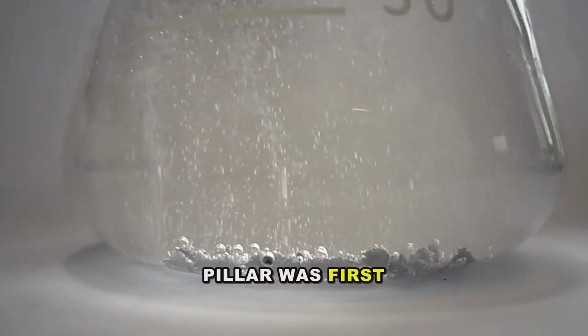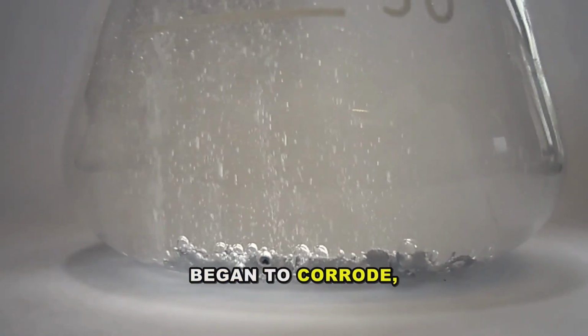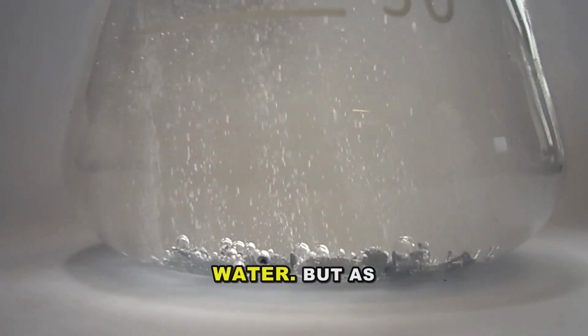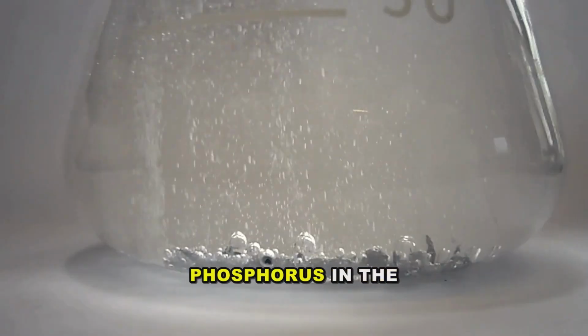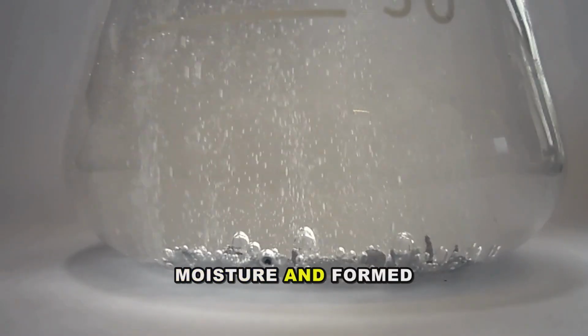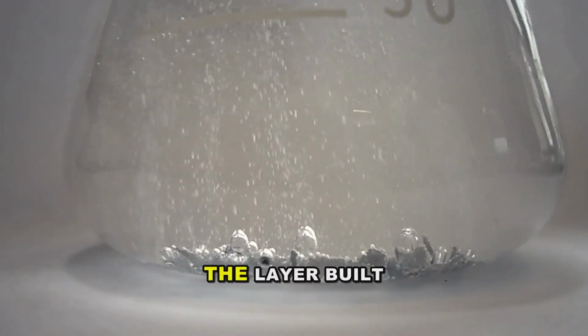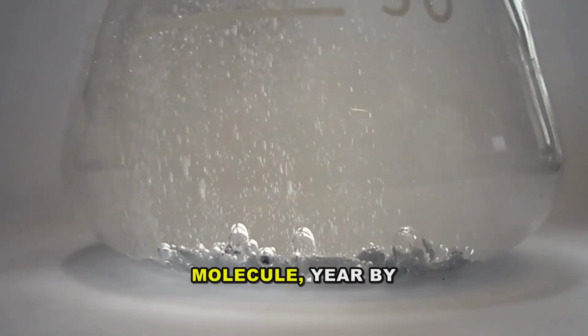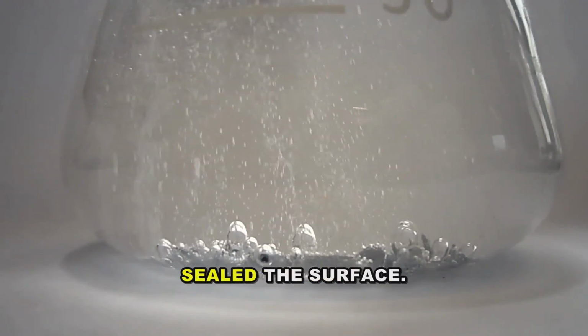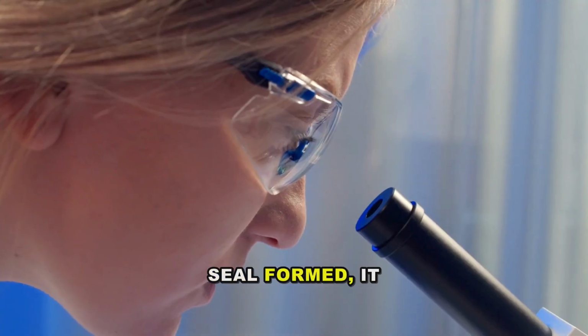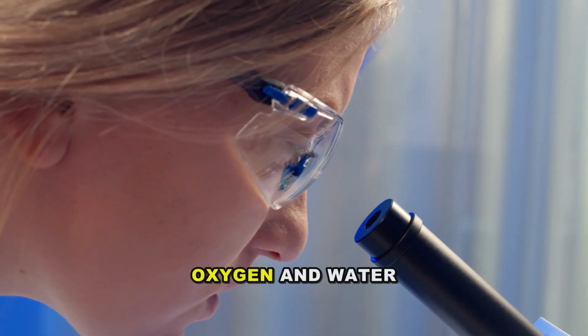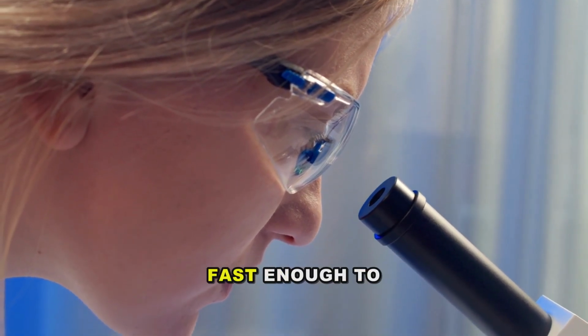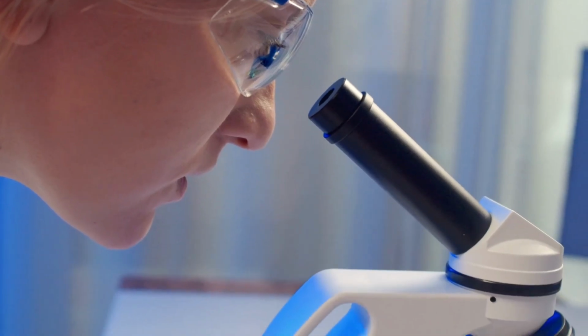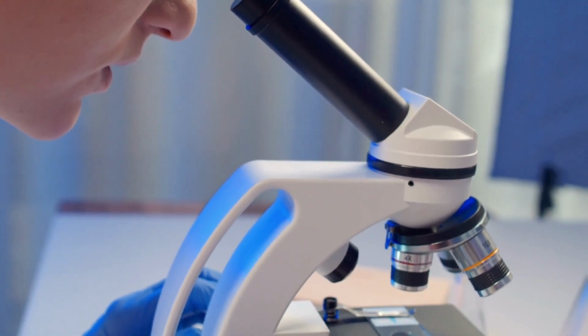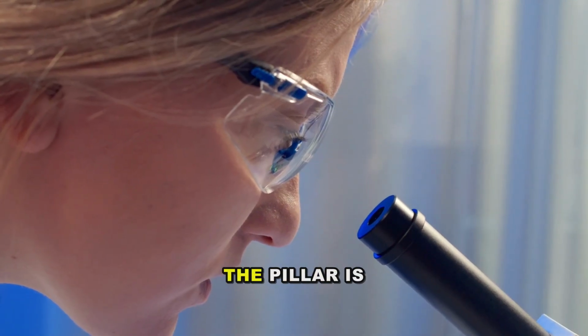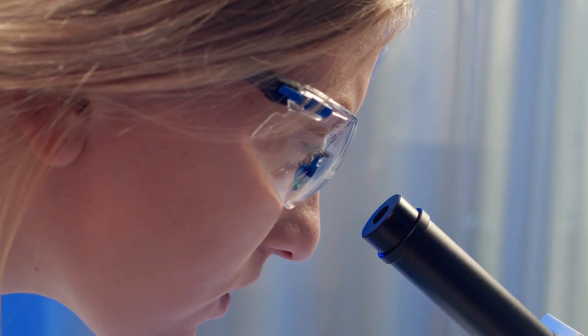When the pillar was first erected, the surface began to corrode, slowly. Iron, oxygen, water. But as it corroded, the phosphorus in the metal reacted with moisture and formed iron hydrogen phosphate. The layer built up, molecule by molecule, year by year, until it sealed the surface. And once that seal formed, it stopped the rust. Oxygen and water cannot penetrate it fast enough to corrode the iron underneath. The layer is self-repairing. If it chips, new phosphate forms in the gap. The pillar is protected by its own weathering.